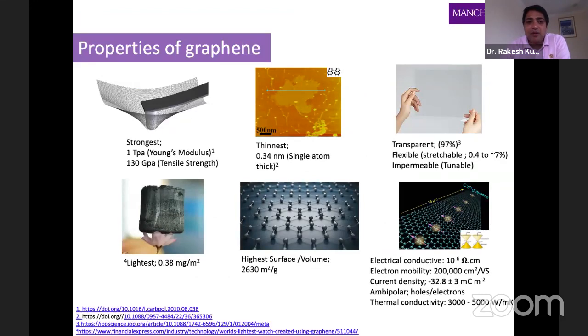So if we look at the properties of graphene, graphene is one of the strongest materials. The Young's modulus for graphene is around 1 terapascal with a 130 gigapascal tensile strength. That's why we say graphene is 200 times stronger than steel. But please, we need to compare it with steel when it is in a single layer form. We cannot compare steel in a bulk form with graphene. It's the thinnest material because it's a single atom thick, and the atom diameter is around 0.34 nanometer. 97% of light is transmitted, so graphene is transparent. It's also very flexible. It can be a good material for flexible and transparent electronics.